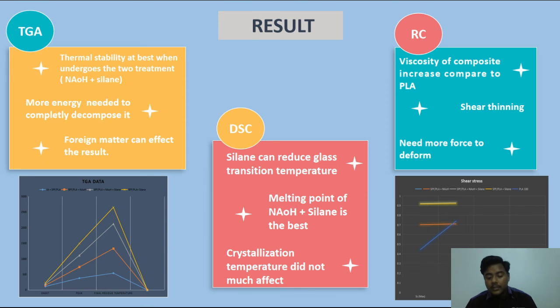Okay, the last analysis is the rheological studies. We can say that the viscosity of the biocomposite has increased, or is higher, compared to pure PLA, and all the graphs show a shear thinning fluid pattern, where the viscosity is declining as the shear is increasing. Among all the samples, the best properties for rheological studies also go to the NaOH plus silane treatment sample, which has the highest force needed to deform the material at different speeds.